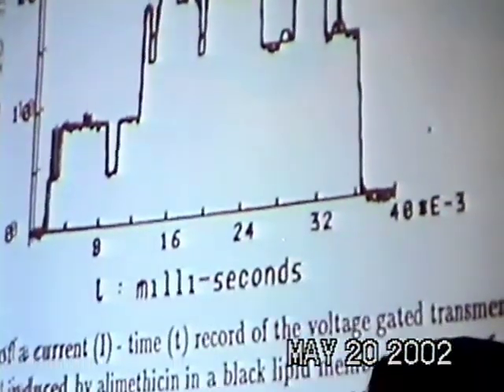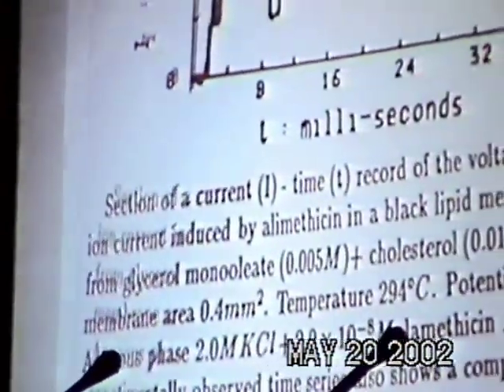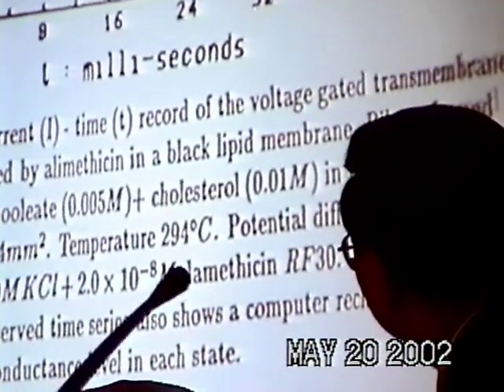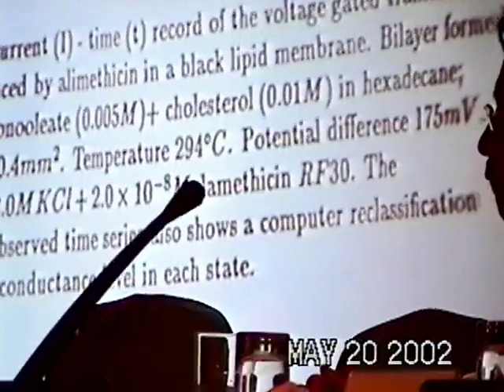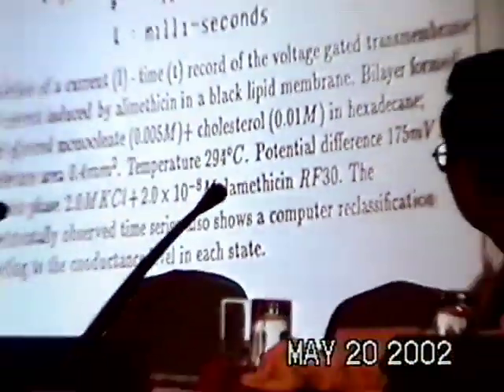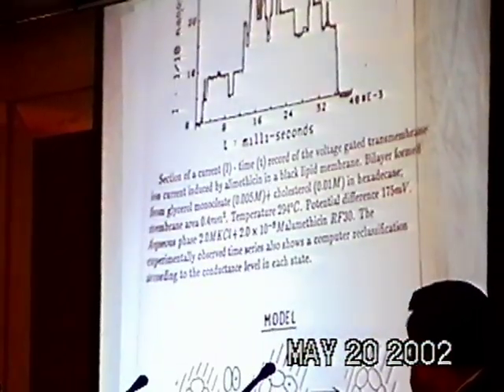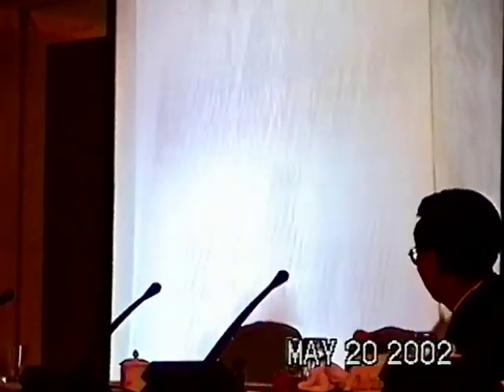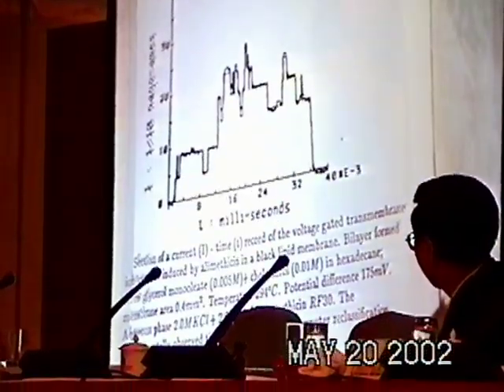Well, it's been known for a long time that if we have a pore-forming molecule like alamethicin, which is a polypeptide, we get discrete conductance states in the membrane. And this is an actual section of a time record of the transmembrane ion conductance, showing transitions between adjacent states. Note there are only transitions between adjacent states. I should point out that this is an ideal object for investigation by electrochemistry because we can get the energetics in each state by the residence time from the Boltzmann law, and we can count the number of transitions, so we can do the kinetics at the molecular level.